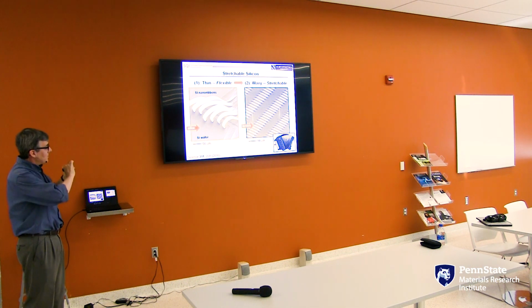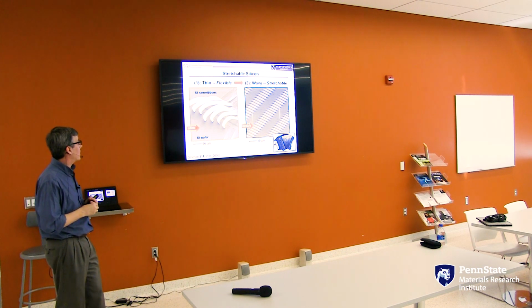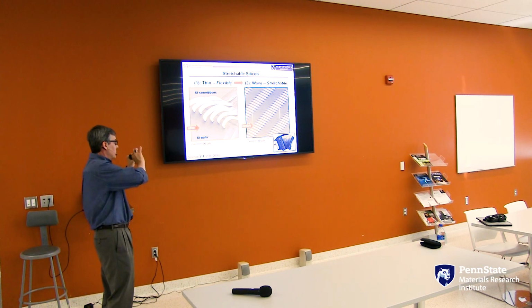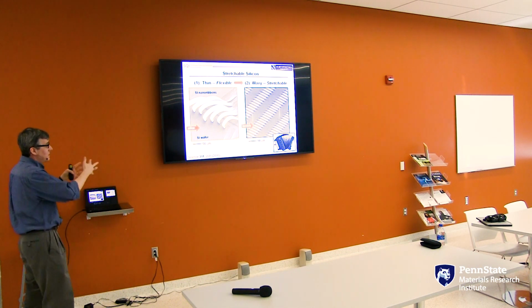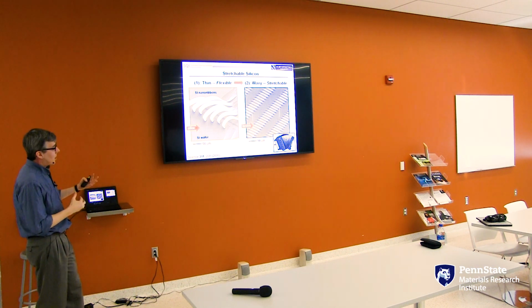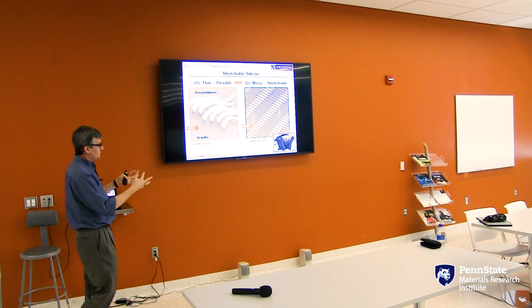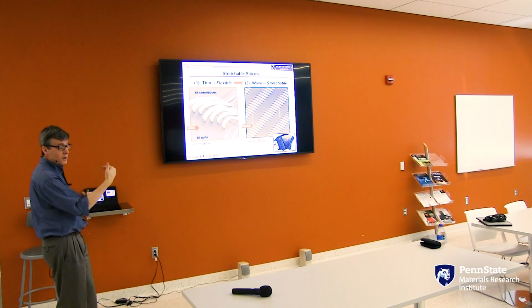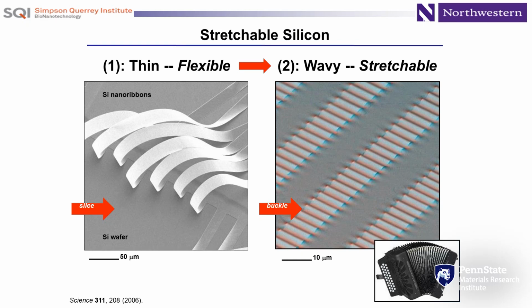And so you add another simple idea on top of this observation that thin materials can be very flexible, even if they're high in modulus and relatively brittle, by taking those strips and then bonding them with an underlying elastomer substrate, but not bonding them in a flat geometry, in sort of a wavy buckled shape. And so in this way, you create a hard, soft composite material that offers the stretchability defined by the substrate, but with the electronic properties defined by the hard material component, where you can think about this combined hard, soft material structure as having a physics of an accordion bellows, in a sense.